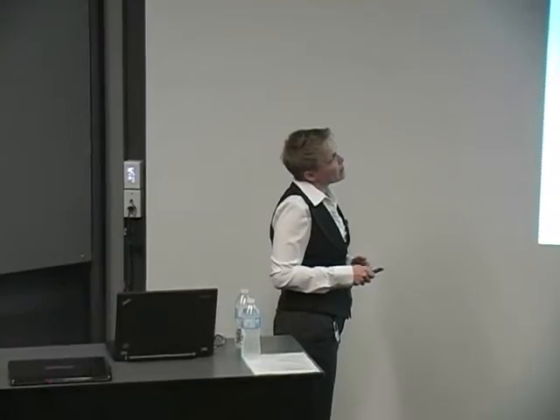And we see that, in fact, up until 10 to the minus 5 molar, there's no increase in self-discharge. We need to get to a 10 to the minus 4 molar concentration of iron before we start to see an increase in self-discharge. 10 to the minus 4 molar, 10 to the minus 3 molar, that's about where we would have the iron contamination in an industrial sulfuric acid. So that's coming from the drums and then from the instruments the supercapacitors are made with, or the machines. And so what we're seeing is that, yes, iron will cause some self-discharge, but at concentrations higher than we might have previously predicted.